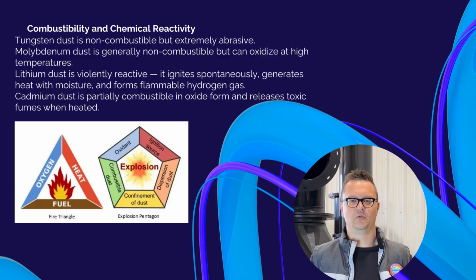Combustibility and chemical reactivity. These four metals represent all ends of the reactivity spectrum. Tungsten dust is non-combustible but extremely abrasive. Molybdenum dust is generally non-combustible but can oxidize at high temperatures. Lithium dust is violently reactive. It ignites spontaneously, generates heat with moisture, and forms flammable hydrogen gas. Cadmium dust is partially combustible in oxide form and releases toxic fumes when heated. Lithium is the most reactive of the four and requires Class D safety measures.